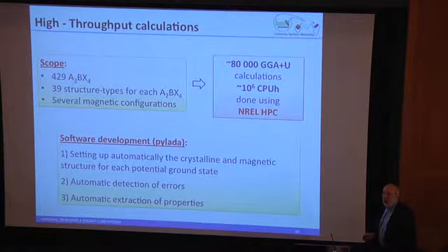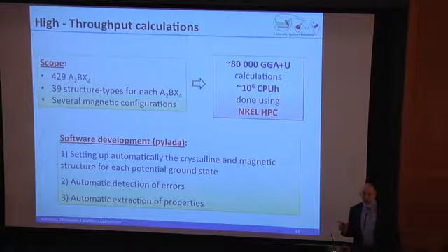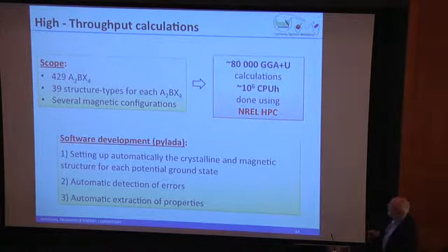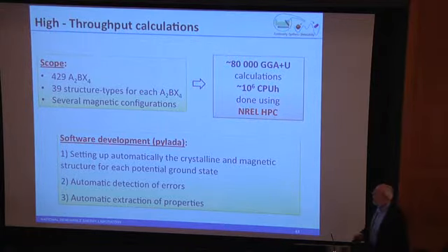Fortunately, NREL has Peregrine, which is a petaflop machine. You have to do essentially 80,000 GGA plus U calculations. When we first started Peregrine up, we used 100% of its time, and we were told that was unacceptable. I don't know why. Something about other funding. And then we've developed this pylada algorithm which helps detect errors and makes the calculation much quicker.